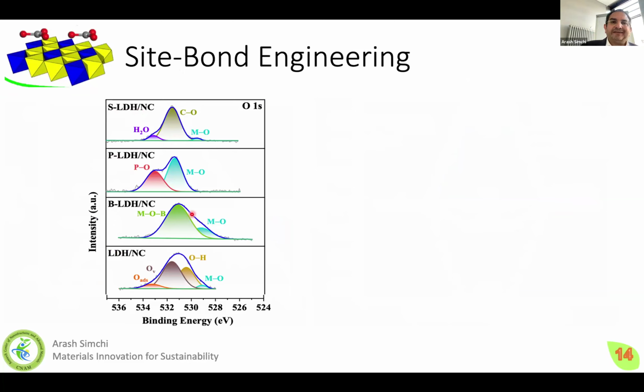I just want to show you one example of XPS data. So we synthesized LDH. We incorporated sulfur, phosphorus, boron, and so on inside the structure by very simple chemical methods. We do not use very expensive or high temperature chemistry. We just try to use green chemistry type approaches. What I would like to show you in this XPS data, as you see here, is oxygen adsorption and oxygen vacancies, and also metal oxygen bonds forming.